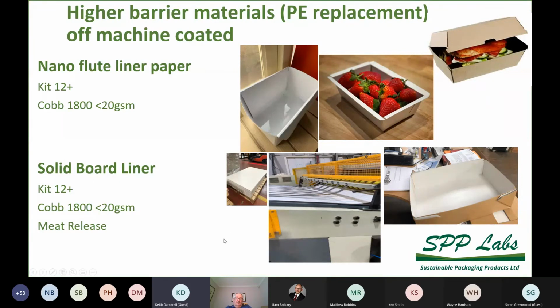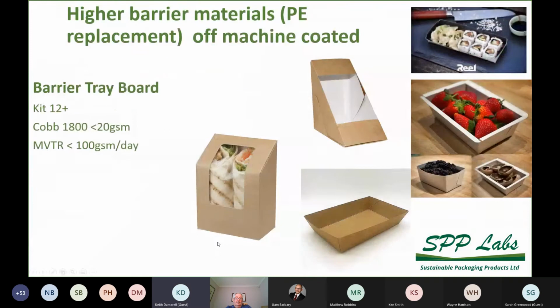If we move on to the next slide, you might have to click twice, Liam. That's coating a liner and then making a corrugate or a laminate board. You can also coat now directly onto folding carton materials to produce high barrier performance. Again, similar barrier functionality, high grease resistance, high water resistance, some levels of MVTR that can be made suitable for hot and cold food, and essentially is replacing what is typically 12 grams of polyethylene that is today usually extruded onto a folding carton material.